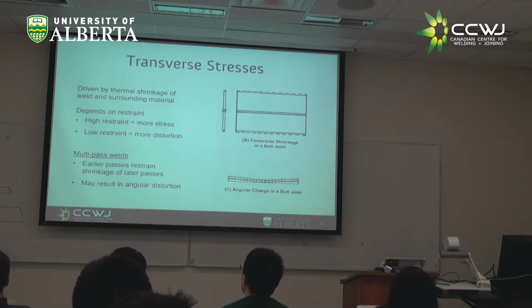And typically this can be a real big concern if you have high restraint, because as you imagine that as you get to the outside, you actually start to maybe bend across the root. And bending across a root is typically very, very bad in welding. You put high tension stresses across the root, and if you have a little bit of a notch here, just from the geometry of when you're actually putting that pass in, if you're going from the outside, if it's a pipe, you don't have access to the inside, you might not have a perfect geometry. Now you're bending across that imperfect geometry, and it's the worst case scenario for forming cracks or other defects. So it's a big concern.